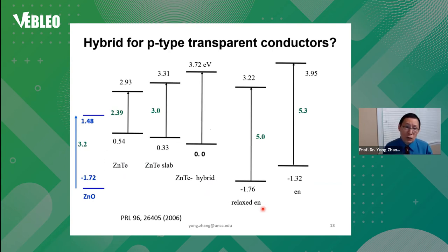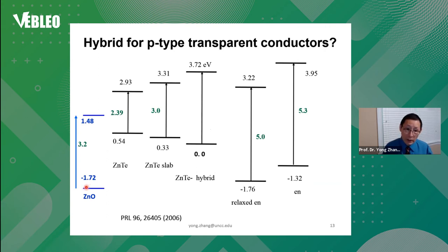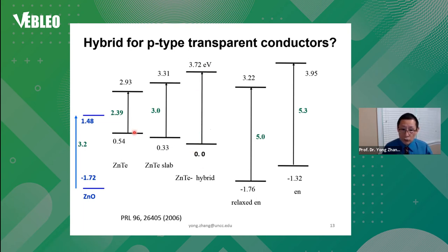There's another possibility to use this structure for P-type transparent conducting materials. People are very interested in making high-bandgap oxides P-type conducting, but there is a fundamental challenge: the valence band of these oxides tends to be very low relative to the vacuum level. Zinc telluride can achieve the highest P-type conductivity among 2-6 materials because it has a very high top valence band. In this hybrid, the valence band is only dropped by a few hundred meV, still way above the oxides. Combined with a bandgap larger than ITO, this gives a very nice transparent P-type conducting material.